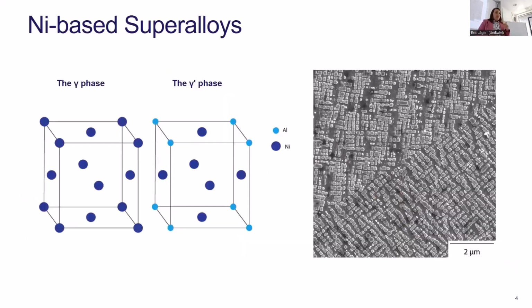So very briefly, nickel-based superalloys, if you're not familiar, primarily consist of two phases. The gamma phase matrix, which is an FCC nickel-based solid solution. We like it, it's nice and ductile. It has low rates of self-diffusion, so its creep is quite good. It has good solubility for lots of different elements, so we can tailor it quite nicely. But we can supercharge those properties by using the precipitation of the L1_2 gamma prime phase, which is a Ni3Al ordered intermetallic. And using that, we can increase the temperature capability and mechanical performance significantly.